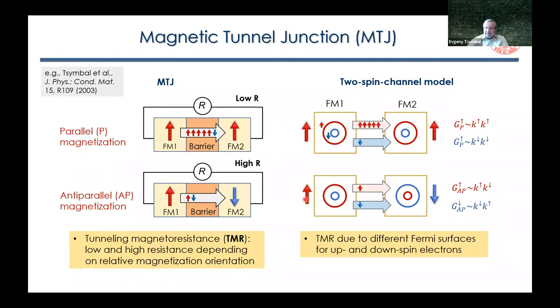So one can simply interpret this in qualitative terms in a way that we have either matching or mismatching of the Fermi surfaces, because in this case, majority spin electrons are coupled and the tunneling is allowed between up and up spins in both ferromagnets.